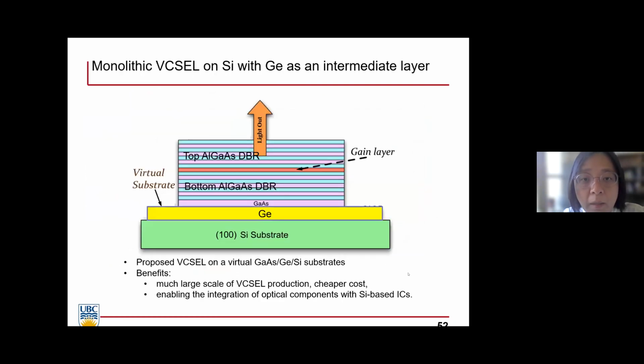So how do we enable mass production of these VCSEL lasers? One thing we looked at is to have silicon be the substrate instead of the gallium arsenide substrate. The reason is that gallium arsenide is not good when scaled up. It's a very brittle material, whereas silicon is very robust. It can go to 12-inch, 18-inch. And germanium is here as a transition layer, really to lattice match to gallium arsenide.